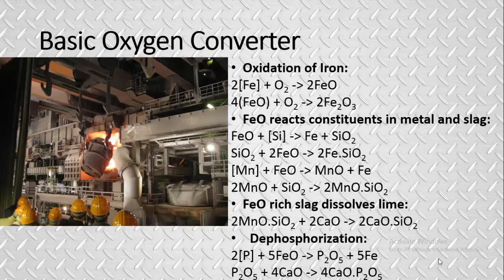Now comes the basic oxygen converter, or BOC. It is the most abundantly used process for procuring steel from pig iron. The basic oxygen converter can produce up to 250 tons of steel in a matter of hours. The iron is first oxidized to iron oxide by directing oxygen at molten metal at supersonic speeds. The iron oxide then reacts with the impurities in the metal and the slag.